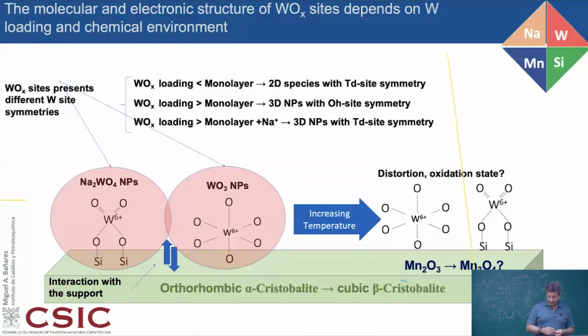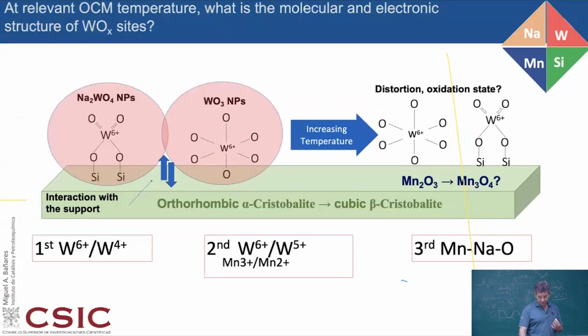And we make, in the case of silica-supported sodium tungstate modified with manganese, you may have multiple scenarios. At low loading, tungsten or wolfram will be dispersed at the surface of the silica support. If you go to the monolayer, you will get WO3 crystallites. And if you are adding sodium from very low loading, there will always be an affinity between tungsten and sodium. And also the environment changes because the dispersed tungsten can be mainly tetrahedral, octahedral when it is crystalline, and then tetrahedral again when it has sodium and it goes into the different kinds of tungstates. So you can get already information from these kinds of cases.